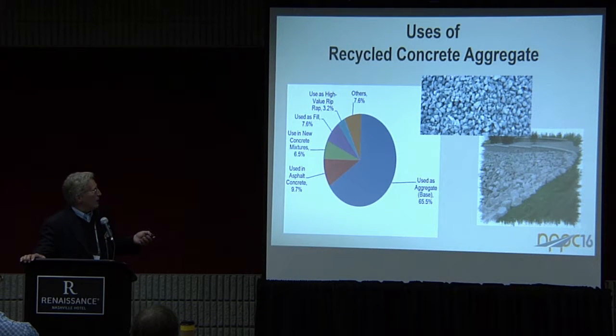But we also see some higher type applications, see it being used back into new concrete mixes, both in single lift conventional concrete paving construction, as well as in two-lift paving construction. We're seeing a lot of interest in using crushed concrete as the aggregate in the lower lift of a two-lift concrete paving system. I'll show you that a little bit later. Actually, more of it is used in asphalt concrete than there is back into concrete mixtures. A little higher demand for the asphalt typically, because the concrete tends to be fairly highly absorptive, so the asphalt demand goes up a little bit, but it is used. Used as backfill, used as riprap like you see here for erosion control, and a lot of other applications as well. I've seen it used as filter materials, as turkey grit for some of the fines. We're seeing it used in a lot of different applications.